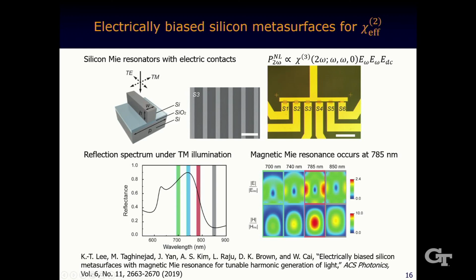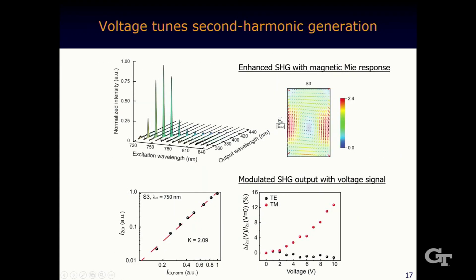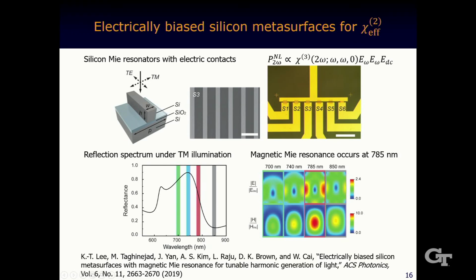Okay, you have the silicon. If you want to enlarge the signal, then you can also make them into a resonator, in this case a Mie resonator, and then apply voltage along the silicon resonators. This will make them very efficient nonlinear optical resonators. For example, we carefully design and fabricate that so that at a particular wavelength, 785 in this case, you can see perfect Mie resonating behavior to excite a magnetic dipole moment. That's another figure. You can see the magnetic dipole moment represented by this circulating electric field. And then when you vary the excitation wavelength with a fixed intensity and see the harmonic generation from such a system, indeed they reach the maximum when you hit this Mie resonance.